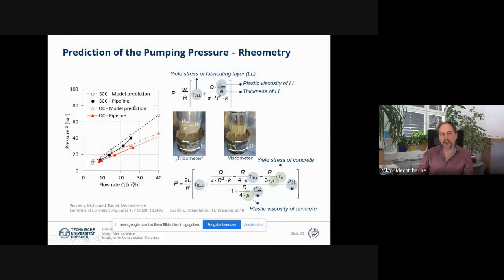So you see here on the left an example that we use this kind of measurements and the prediction and compared the prediction with the real measurement on the pipeline. So the pipeline is given here with solid symbols and with the solid line, while the dashed line and here the empty symbols, they give the prediction. And you see that actually the curves are pretty close together. It seems that this approach works really very nicely.